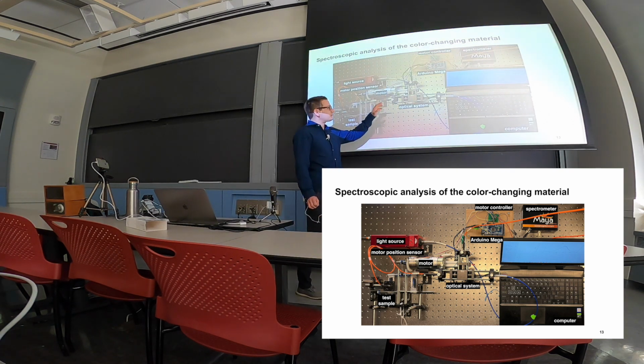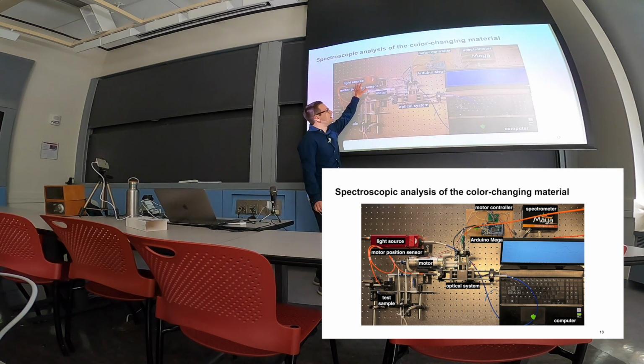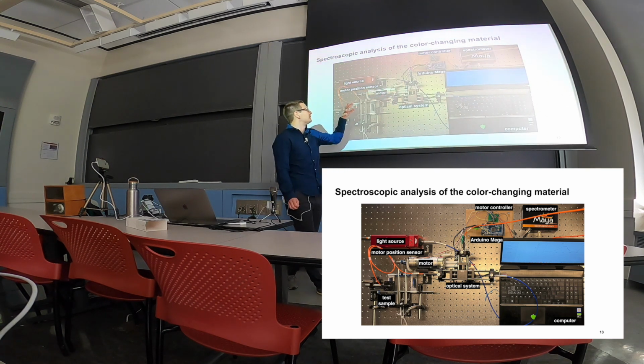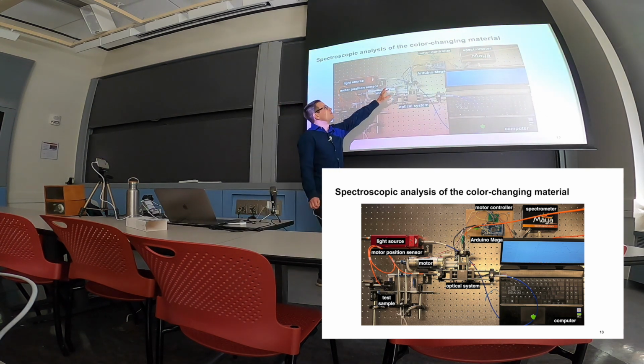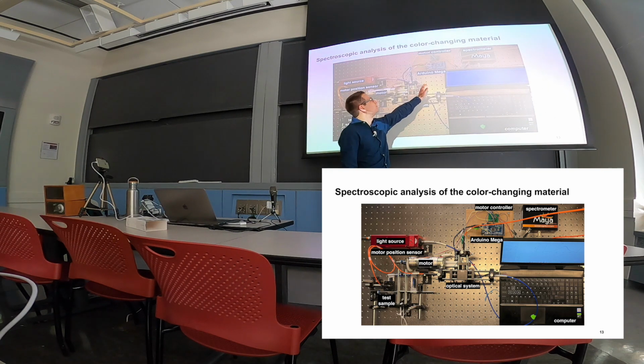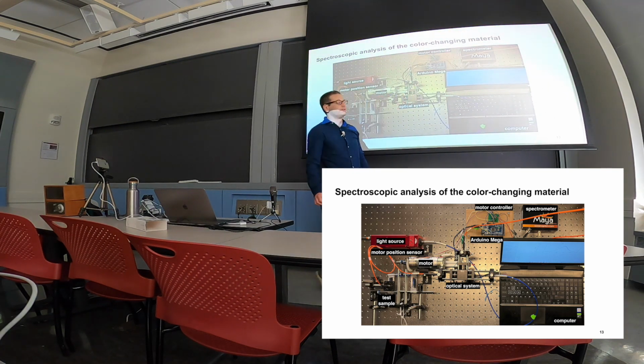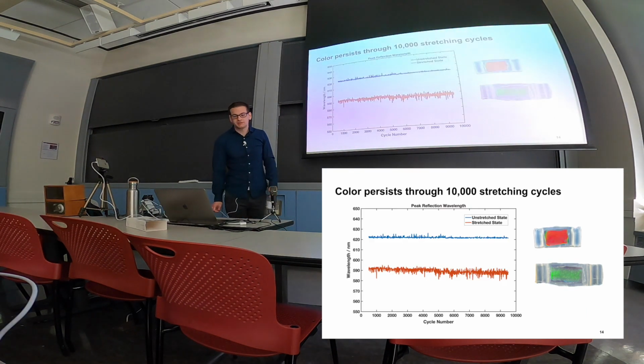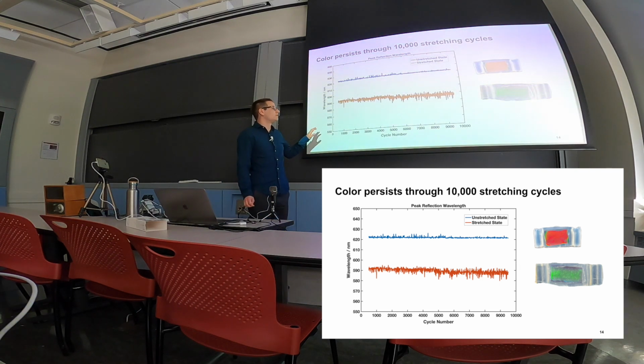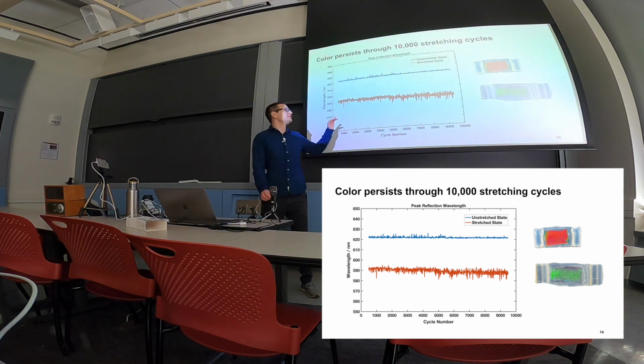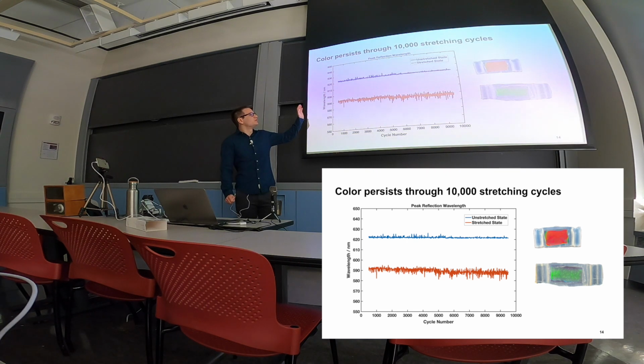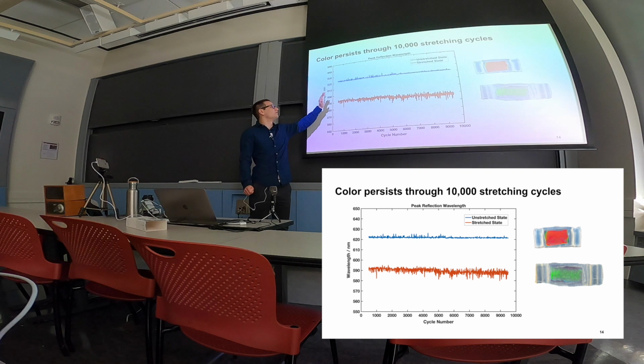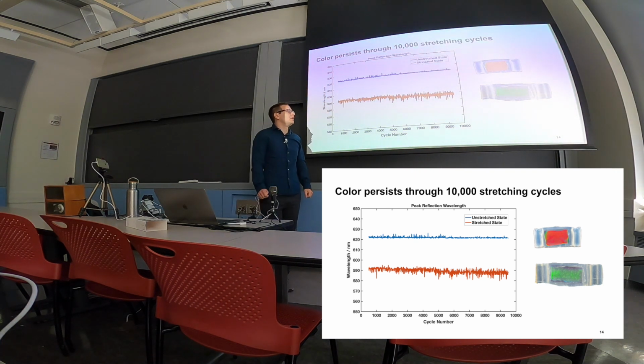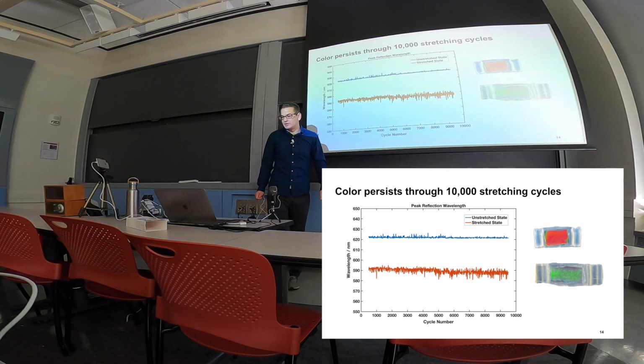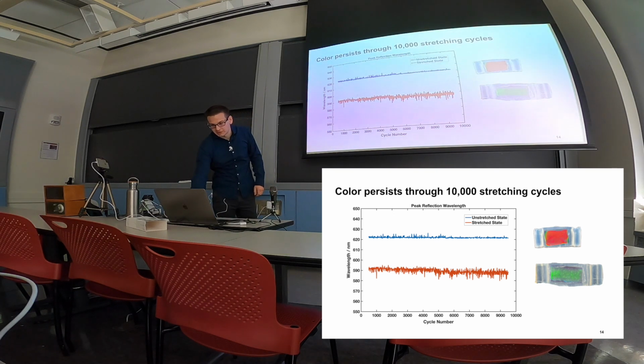So once again, nothing else than the light source being here, that fed into the optical system, the motor that drives the stretching of the sample, the motor controller for controlling the driving speed of the motor, and the spectrometer at the top right over here. And we see that the results with the 4-layer approach have been way better. So over a course of 10,000 cycles of stretching, there's almost no aging taking place. So we can say that in the stretched and unstretched state, unstretched state at the top and stretched state at the bottom, it's kind of a straight slope, so no aging taking place.